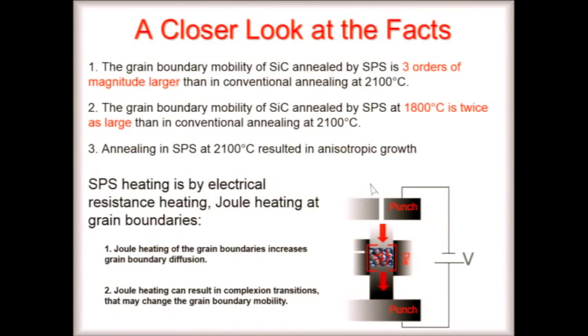What's going on here? Well, I'm not one of those people that says we have a plasma at the surface of the crystals during sintering, and certainly not at the grain boundaries during the grain growth experiment. But if you look at the data I just showed you, and select data, because grain growth experiments haven't really been done very much by flash, the influence of the external field does cause an increase in grain boundary mobility. And this has to be associated with the space charge along the grain boundaries.